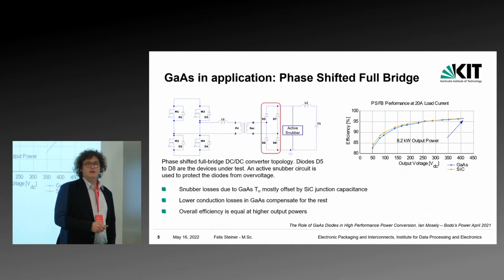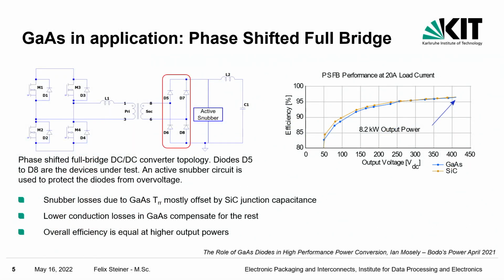So now to some gallium arsenide in application. Ian Mosley did some research on the efficiency, and whether you can use gallium arsenide basically as a drop-in replacement for silicon carbide. Here he used a phase-shifted full-bridge DC-DC converter and replaced the silicon carbide dies in the output rectifier with gallium arsenide dies. And we can see here there's also an active snubber to reduce the overvoltages. By monitoring the snubber voltage, the snubber losses, you can differentiate between the switching losses and the conductive losses.